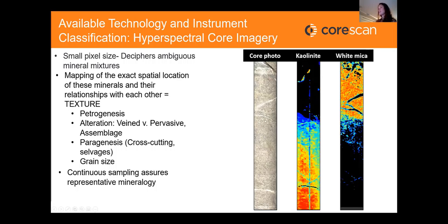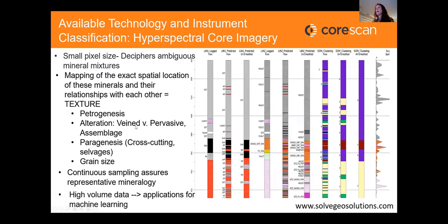Over here on the left, we have a core photo. It looks pretty homogeneous. Over here on the far right is a white mica mineral match. And in the middle is a kaolinite mineral match. And the point I'm trying to make here is that if you took a measurement up at the top of this interval, you would probably have to assume that the rest of your interval was white mica dominant, which might not be the case. It looks like you're switching to a more kaolinite dominant alteration. And lastly, this is high volume data. So there are applications for later on for machine learning.